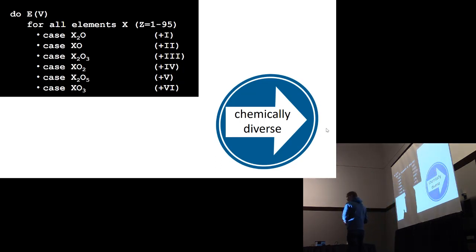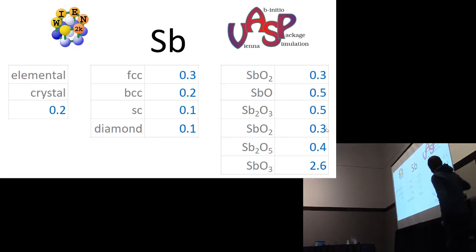Chemical diversity. Well, here we propose six different oxides that are highly symmetric, that have only the volume as their degree of freedom, so you can easily make an energy versus volume scan. They are chosen in such a way that you cover all the oxidation states of the non-oxygen element. That can be for some elements probably quite weird, so maybe you don't have to do this really for every element. But for many elements that can be a quite exhaustive scan of oxidation states of chemical environments. If you do that for the antimony crystals, then again these delta values are of the same order of magnitude except perhaps for this one which is a bit larger.